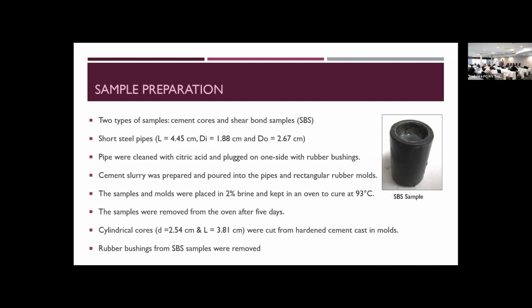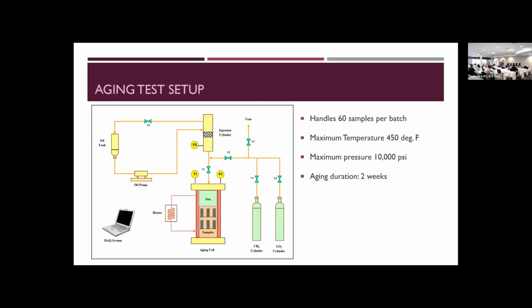We have cement cores and we have shear bond samples that have been used. For the shear bond samples, we use metal pipes, tiny, short pipes, as you can see here, with a length of 4.45 centimeters, an inside diameter of 1.88 and an outside diameter of 2.67. These were cleaned. We pour cement in them, and then we put them in the autoclave and expose them to the CO2 environment. Especially for the bonding samples, we also use as reference small samples, which were originally rectangular samples that we then cored to get cylindrical samples used for testing. I will show you some of the testing results on that one.